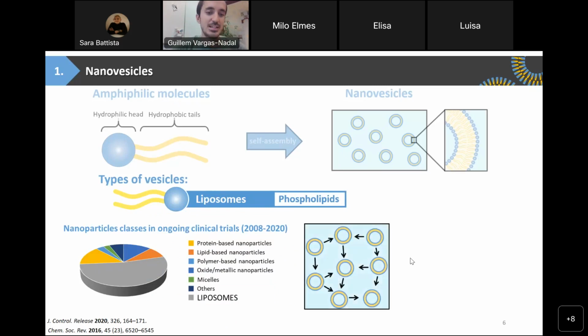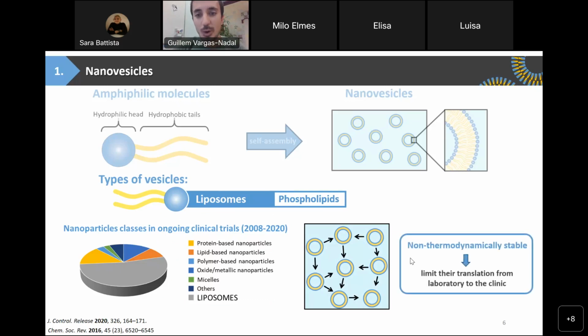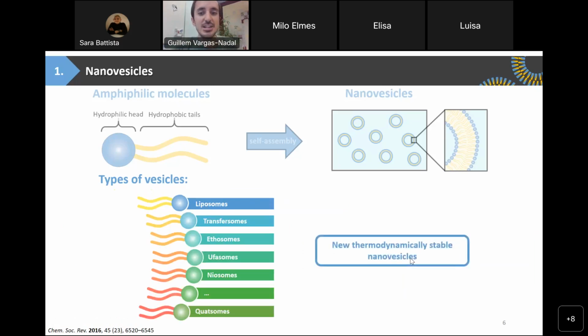However, these liposomes have one important drawback, which is their stability. They tend to interact with each other, and finally they coagulate. So because they are not thermodynamically stable nanoparticles, this is a problem, because this fact limits their translation from the lab to the clinic. So for this reason, the scientific community tries to develop new thermodynamically stable nanovesicles.